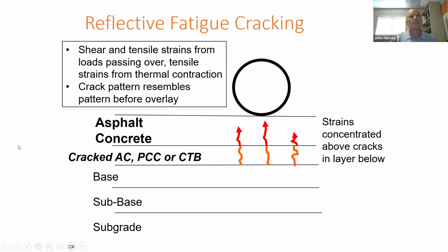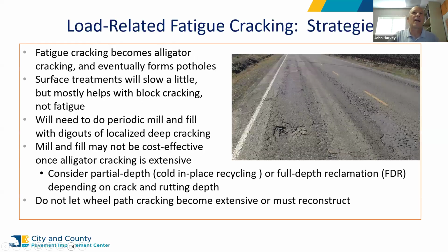that stress concentration. So for load-related cracking, the strategies: it eventually becomes alligator cracking, and then the pieces come out, and that's what a pothole is. A pothole is the whole end of the process. Surface treatments, again, do a little bit to slow that, but really those are about age-related and block cracking. You can do periodic mill and fills or dig outs in isolated areas if you have localized deep cracking, but these become much less cost effective once alligator cracking is extensive.